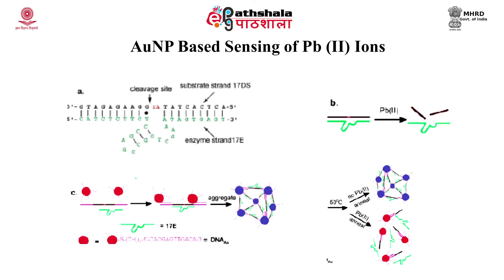Here is an example of the application of gold nanoparticles for the detection of lead ions. In this case, a DNAzyme has been employed as the biocomponent agent. This DNAzyme consists of an enzyme strand and a substrate strand, and includes a cleavage site which is sensitive to the presence of lead ions. The DNAzyme has been labeled with gold nanoparticles. In the presence of lead, the catalytic site is cleaved, resulting in separation of gold nanoparticles and a resultant red color. In the absence of lead, no catalytic event takes place and the nanoparticles remain in aggregated form, representing blue color.